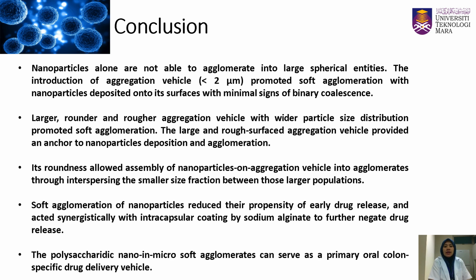The large and rough surface of the aggregation vehicle provided an anchor for nanoparticle deposition and agglomeration. Its roundness allows assembly of nanoparticles on aggregation vehicles into agglomerates through interspersing the smaller size fraction between those larger populations. Soft agglomeration of nanoparticles reduced their propensity for early drug release and acted synergistically with intracapsular coating by sodium alginate to further negate drug release. The polysaccharidic nano-in-micro soft agglomerates can serve as a primary oral colon drug delivery vehicle.